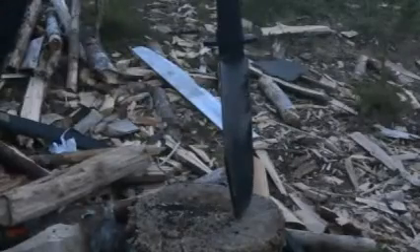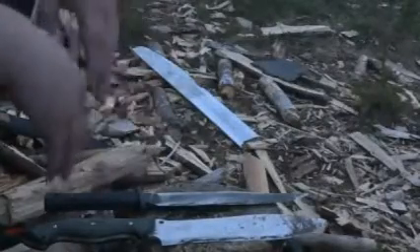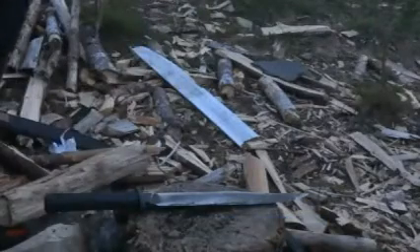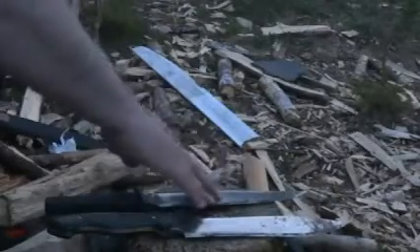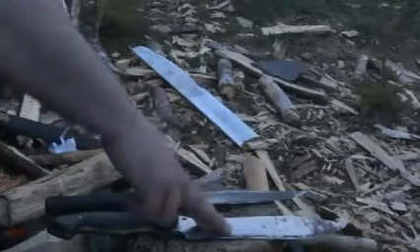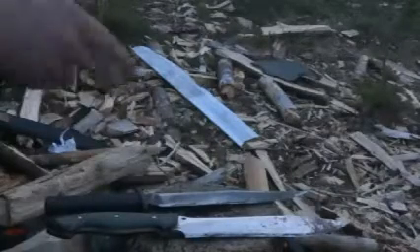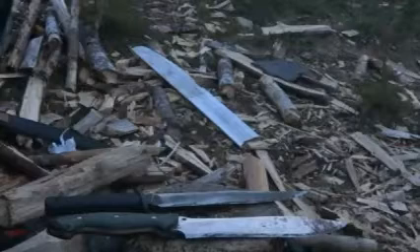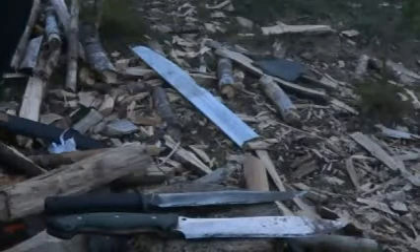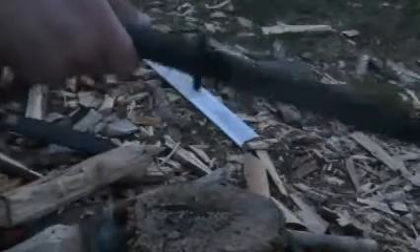Just looking at the blades fairly grossly, comparing them by eye: right here, there's no difference I can see at this distance between the two blades — both are obviously fairly worn. Up close, I can see what appears to be more chipping on this blade and more wear on this blade. That's sort of what I'd expect. This is a high-carbide stainless steel; this is a relatively low-carbide stainless steel, so it will tend to be a bit tougher. But in terms of general functionality, at this point both of them are about the same — they'll have difficulty doing fine work, won't essentially cut paper at all, and will have difficulty cutting light vegetation, cords, and stuff like that. But they're still easily very functional for carving or chopping wood.